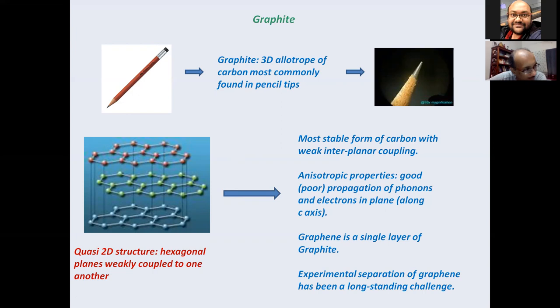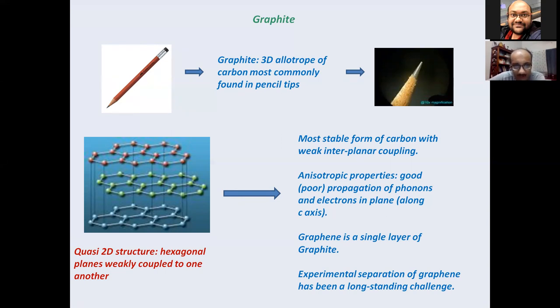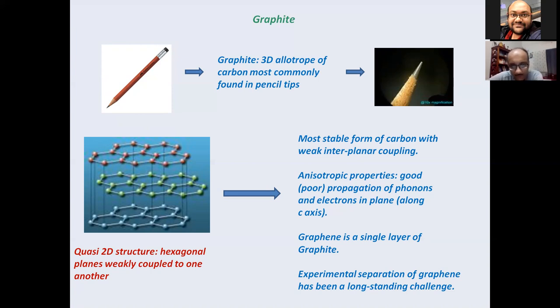Around 1941, K.S. Krishnan first pointed out that graphite has poor propagation of phonons and electrons out of plane and good propagation in-plane. For example, thermal conductivity has a high value measured in-plane, whereas along the C-axis it is rather low. This was done as early as 1941 from IACS, which was one of the very few research institutes in the country at that point.